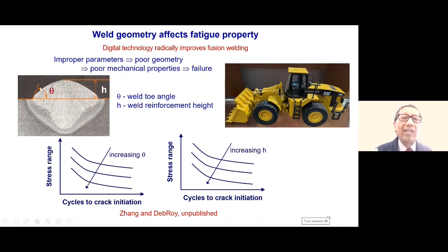This weld toe angle decides whether this edge is sharp or not. If you have a very sharp edge, then the fatigue life would be lower because a crack can initiate and propagate. So improper parameters will give us poor geometry, poor mechanical properties, and God forbid, catastrophic failure.